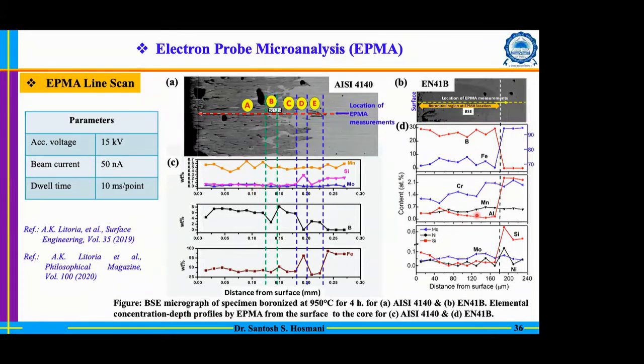And if you look at the aluminum in the next figure, there also in the boride region the aluminum is close to 0. That means there is no solubility at all for aluminum as well as silicon. However, other elements like chromium, manganese, even molybdenum and nickel have some solubility in boride, but that solubility is not the same as in your matrix. That means during the growth of boride, elements will be rejected. That is for sure. Some elements will be accommodated into the iron boride. However, some elements like aluminum, silicon and carbon are entirely rejected, while other elements will be accommodated to some extent, but some portion is also rejected.